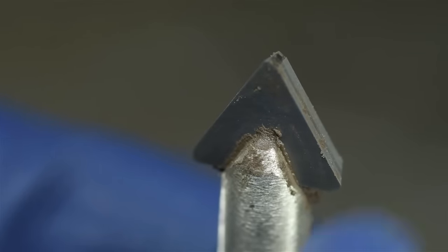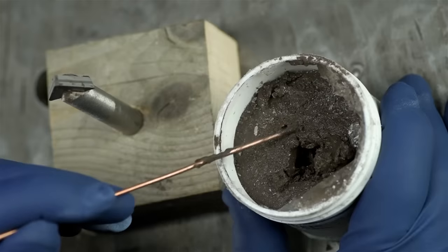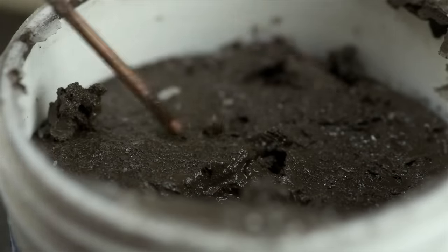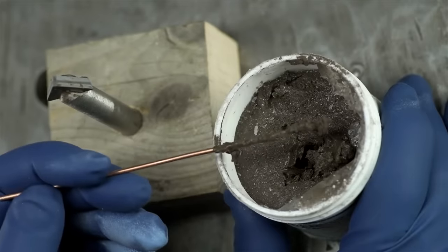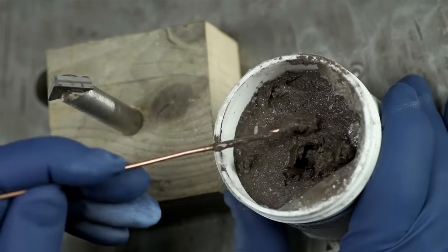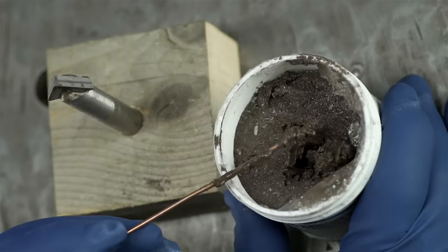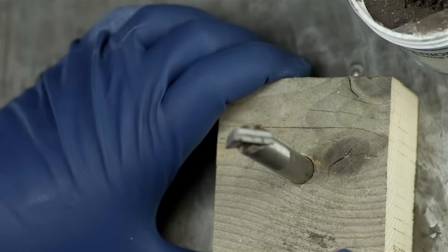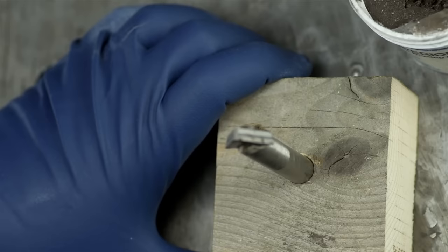If you want to go crazy, you can clean off some of the excess. I've found that the silver only really wants to wet where there's flux. So if you don't want this whole thing coated in silver, just don't flux the whole thing. Taking some care can just help to get a better looking braze joint, if that sort of thing is important for what you're doing. This flux doesn't get used all that often. When I do use it, I don't need much. It has dried up a bit. But if I break through the delicious crust, I can get to the creamy filling, and that's still working well. If it gets much worse, it can be broken up and reconstituted with some water. But that's it. The joint's ready to weld.